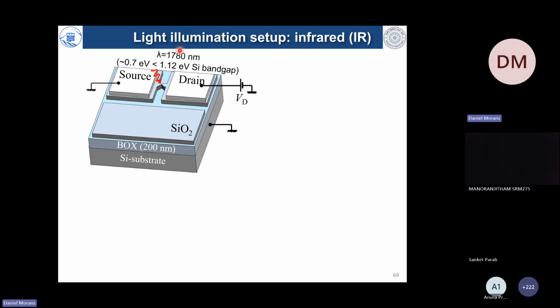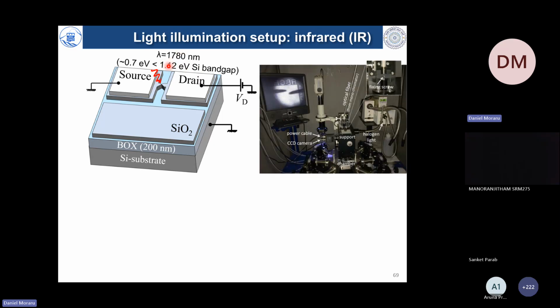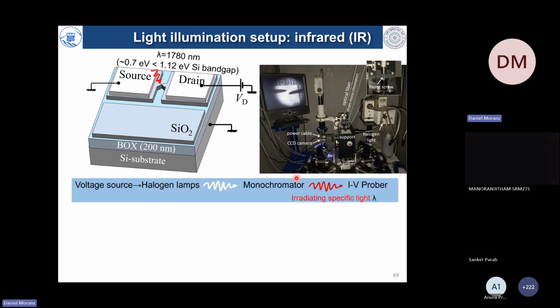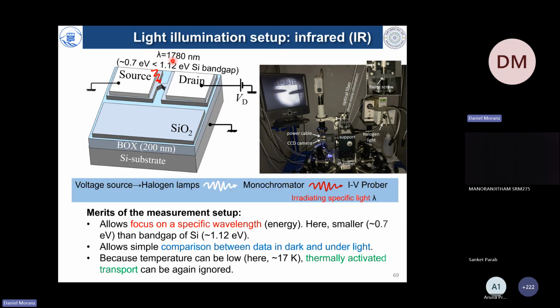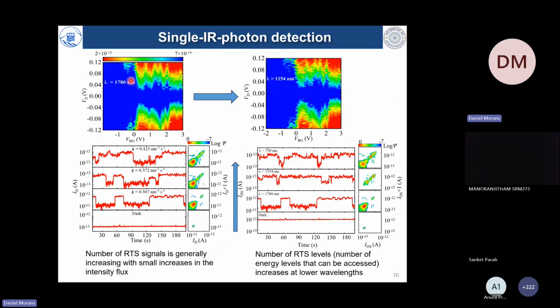However, we are now showing that silicon can actually be used for this using a similar setup, but now irradiating with infrared light. In that case, we are dealing with wavelengths smaller than the band gap, and something happens. I will show you what's going on. If you irradiate with 1780 nanometers, you can still see, compared to dark, 2-level or a little bit triple level RTS in our devices.